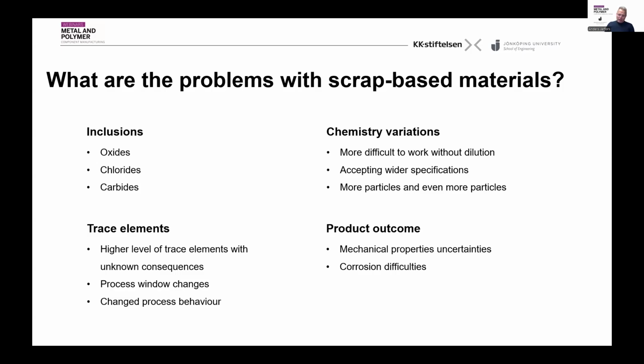Now, trace elements, as we understand now, have somewhat uncertain consequences. Maybe they just act on viscosity, maybe they change surface tension, and that means fillability and pore formation and such are issues. And as Carl Magnus showed also with the heat treatment windows, there is an issue that these windows may disappear with the addition of some copper, for instance, as a trace element. So all these process window changes and changes in processing behavior are uncertainties that we need to be able to understand and deal with.